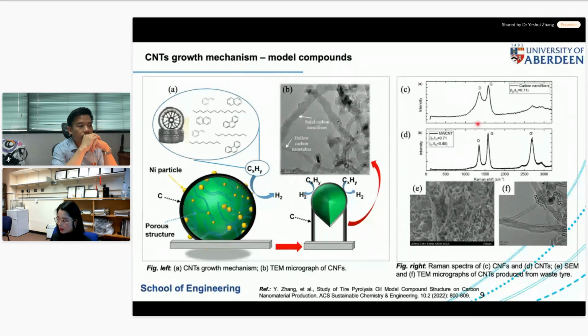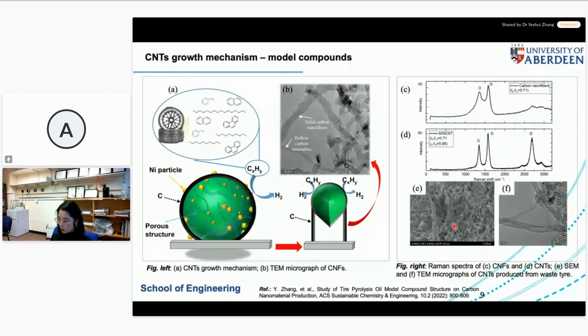And on the right-hand side, in the figure, we use Raman spectroscopy to confirm the quality of the CNT produced from this process. And I'm sure some of you have been using Raman spectroscopy. It's very powerful equipment to help us identify the amorphous carbon and graphitic carbon from the mixture of these samples. And we do use scanning electron microscopy, like figure E here, and transmission electron microscopy to confirm the production and the quality of the CNTs we produce.